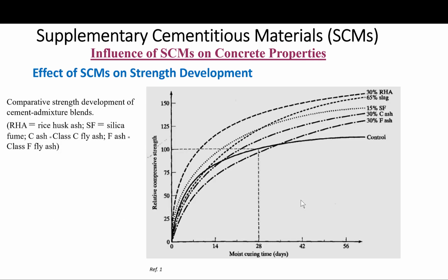This figure shows the effect of adding different mineral admixtures to strength. Let's talk about the control mix, shown with the solid line. You can see the Class C, Class F fly ashes, and the slag replacements all have lower early strength, up to almost 14 days, and almost up to 28 days for Class F fly ash. After that, they all show higher strength.